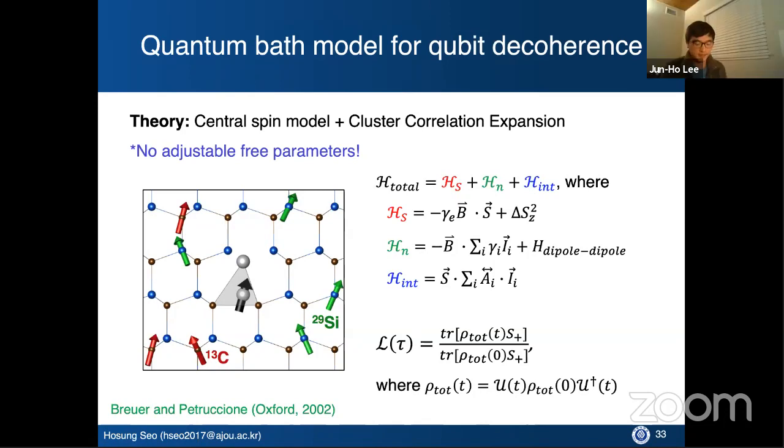So do you mean that in the low temperature limit, electron-phonon interaction will not affect much? Yes, because electron-phonon interaction gives you the T1 relaxation time. T1 is when your spin is flipped and your population changes. That basically gives you the fundamental limit to T2, the coherence time. So fundamentally, T2 is limited by 2 times T1.